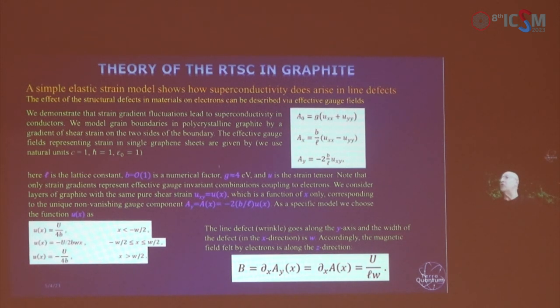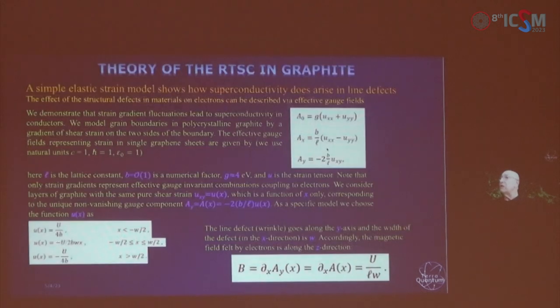We model grain boundaries as a gradient of a shear strain on the two sides of the boundary. And then we immediately introduce the effective gauge field related to strain. This is a more or less standard relation, where L is the lattice constant, we have some numerical factor, an energy constant, and the strain tensor. And then only the strain gradients represent effective gauge invariant combinations, which are coupled to the electrons.